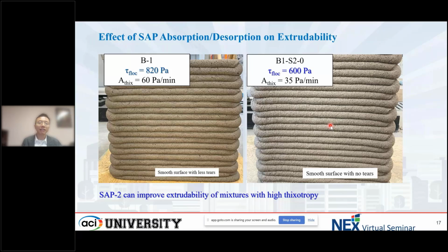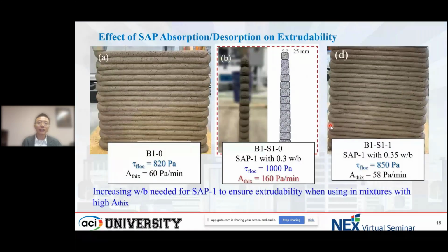But how about the effect of SAP1? The SAP keeps absorbing water gradually. So figure A is still the reference mixture. And then when we add SAP, it increases the floc and also significantly increases the Athix from 60 Pascal per minute to 160 Pascal per minute. Yes, we still got a very good surface quality, just with a little bit more tears,